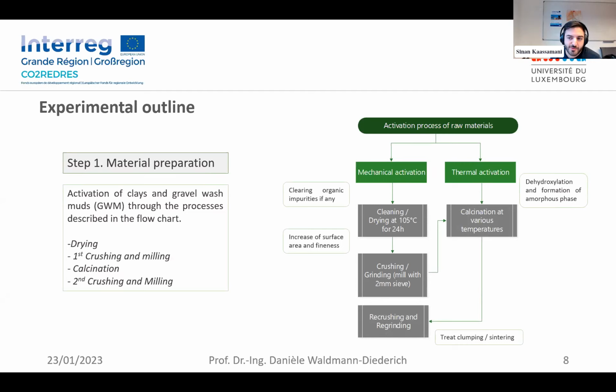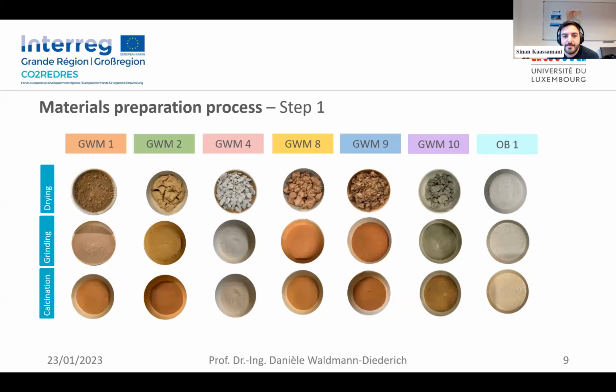By thermal activation, of course, we want to achieve dehydroxylation and then formation of more amorphous phases that are more reactive as well, right? So these are the materials that we used again, but we can see them in their 3 states. So the dried material, and then under it we have the ground material, and then the calcined material. So you can see the change in texture and in color for almost all of them. And from now on, the results that we see are color coded. So everything that's orange would be related to GWM1 and so on.